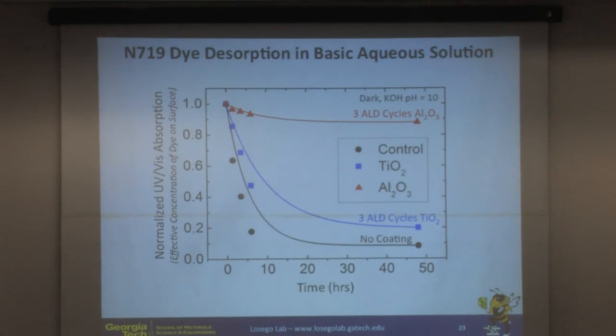So if we actually look at this quantitatively, we can track the UV-Vis absorption of these slides in this pH 10 environment as a function of time. And we see that, yes, without a coating, we can strip off all of the dye within about 12 hours or so. The TiO2 coating in this case gave us some improved stability. The alumina coating gave us very good stability. We retain about 90% of the dye molecules after even 50 hours in this very aggressive high pH environment.